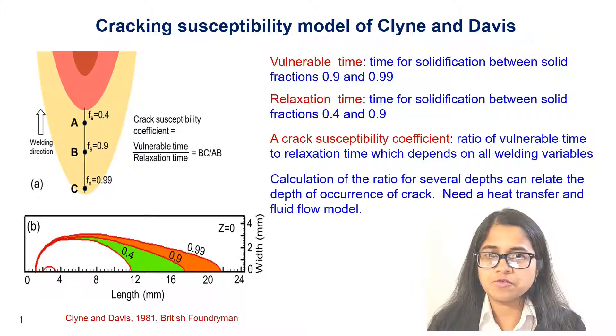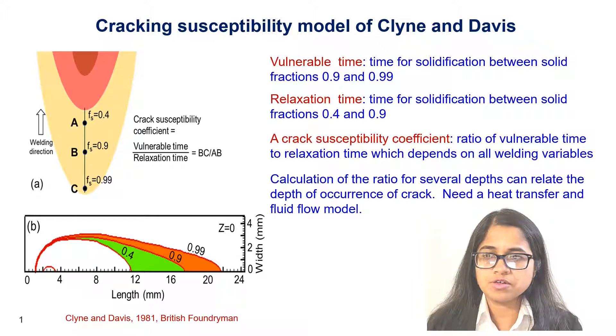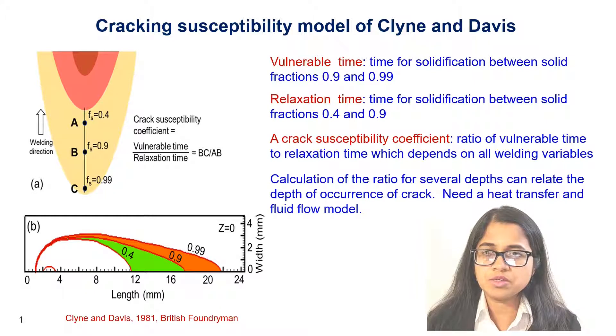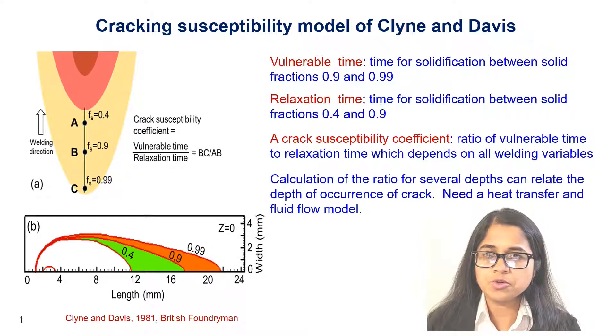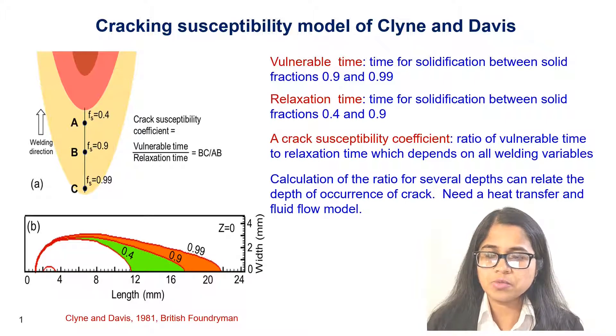During solidification, the formation of increasing fractions of solid with decreasing temperature occurs as the two-phase mixture cools. The time required for the solidification of the two-phase liquid mixture from solid fractions of 0.9 to 0.99 is the vulnerable time. During this time, the liquid available in the two-phase mixture is insufficient to compensate for the shrinkage as the two-phase mixture cools. The relaxation time, on the other hand, corresponds to the time during changes in solid fractions from 0.4 to 0.9.